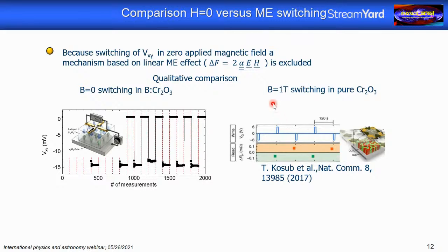However, they always had to have a magnetic field present, actually a quite big one of the order of 1 Tesla, to achieve this type of switching. And notice also that the switching is symmetric between negative and positive resistance values. And that is very, very different in our case. First of all, we apply no field. By the way, this switching here in pure chromia is obviously a symmetric switching between different Hall voltages, and that is a fingerprint of the 180-degree rotation of the antiferromagnetic Néel vector.